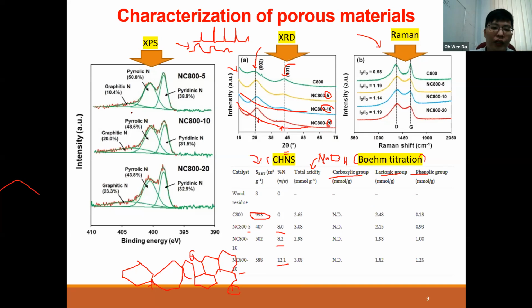So XPS, as I said, looks into the bonding configuration, right? Once you have the nitrogen group, you know that you have the percentage of nitrogen up to 12.1. If you only use CHNS, you only know up to that point. So to bring it one level higher, we take this XPS, and then we carry out the high resolution XPS study to look at the nitrogen site. All these, they are nitrogen. And from the nitrogen XPS spectra, we can see something like this, this peak. And then we do some deconvolution using a software, and we find out that it can come from 3 peaks. So this peak 1, peak 2, and peak 3, right?